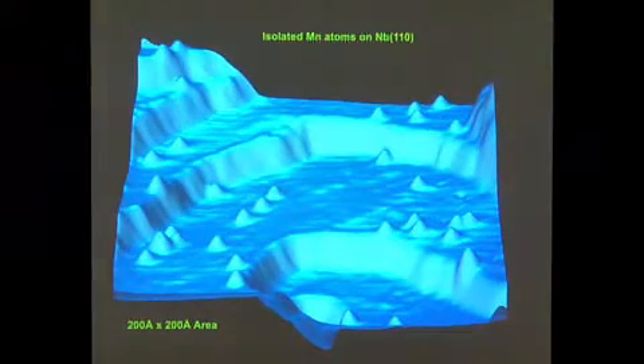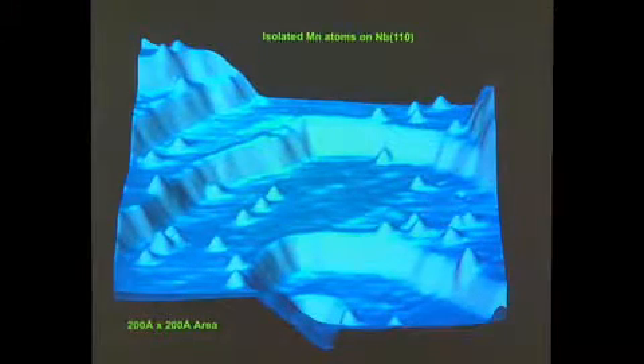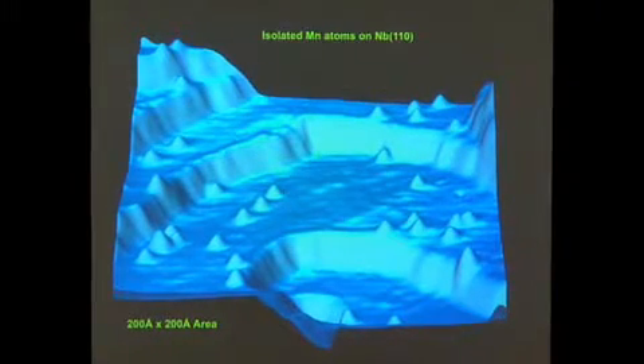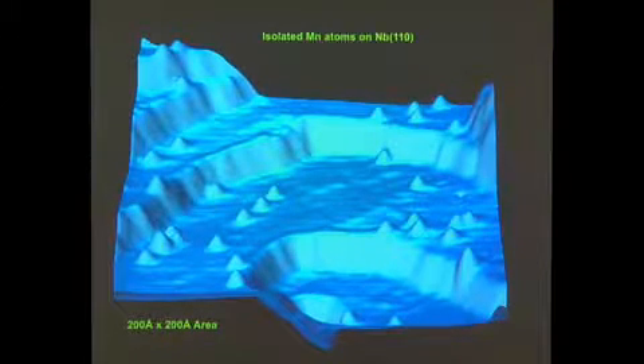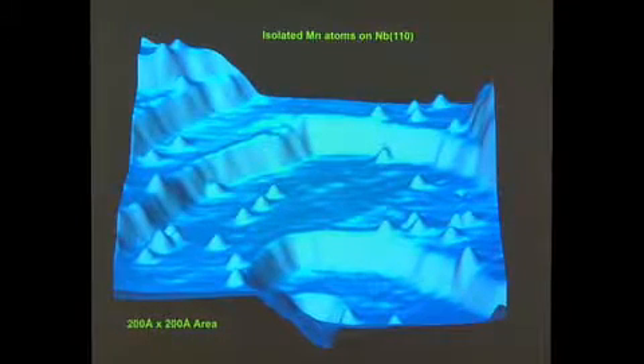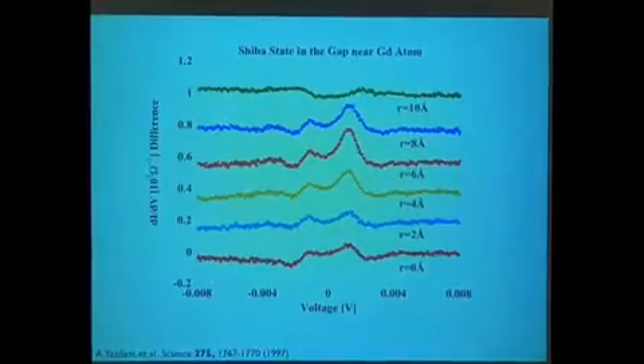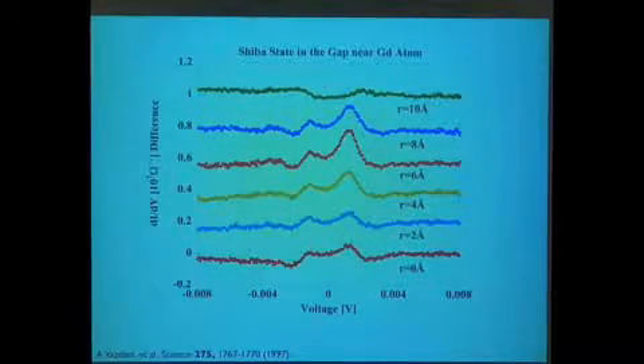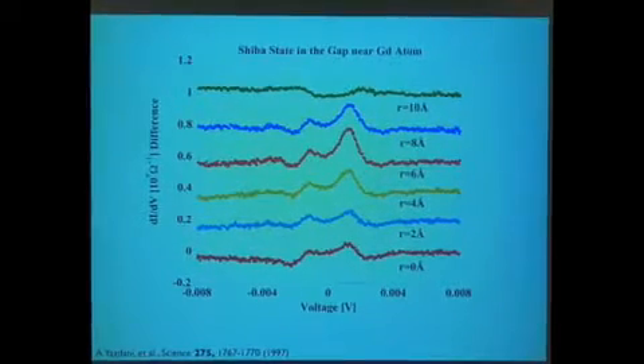Now, you can actually detect these. I did this experiment many years ago, and here it's being repeated now in my lab. Here's the surface of niobium. These are manganese atoms on the surface of niobium. You can make niobium even cleaner than this, but this is pretty good. This is looking at the density of states, focusing on states inside the gap, showing how when you go near a magnetic impurity, you have states that live at low energies. These are those bound states to this impurity coming from the exchange interaction.